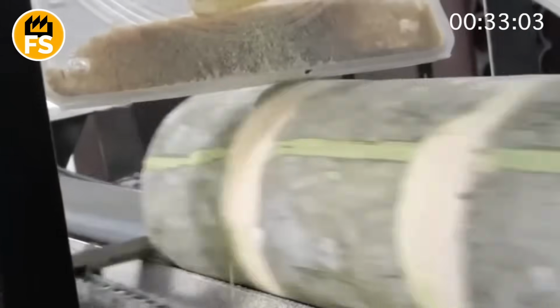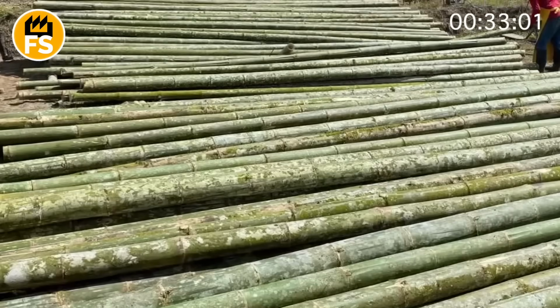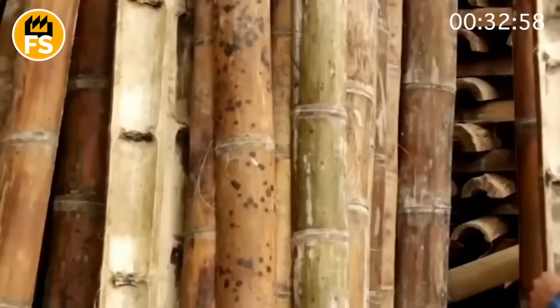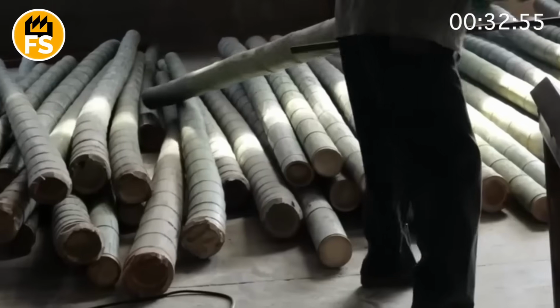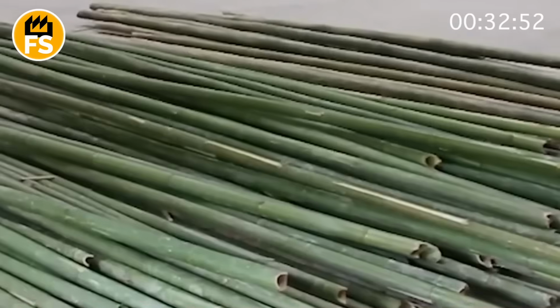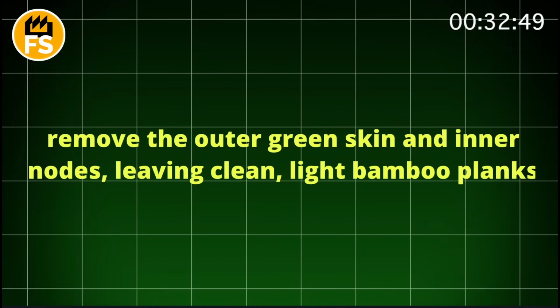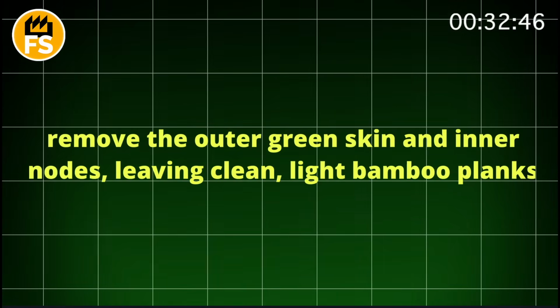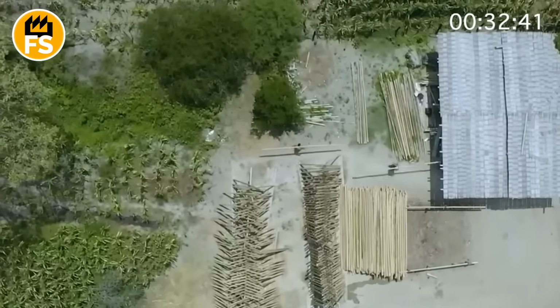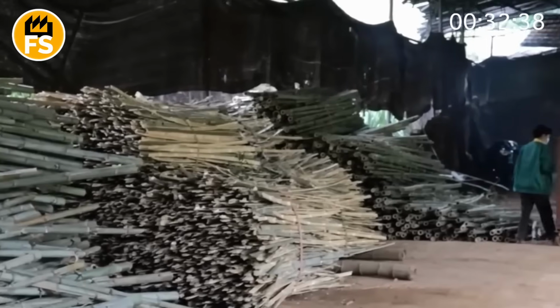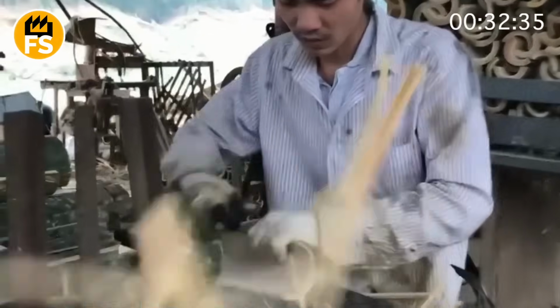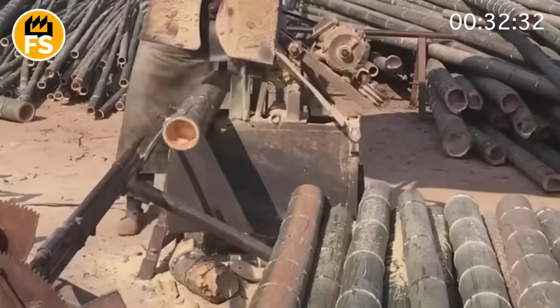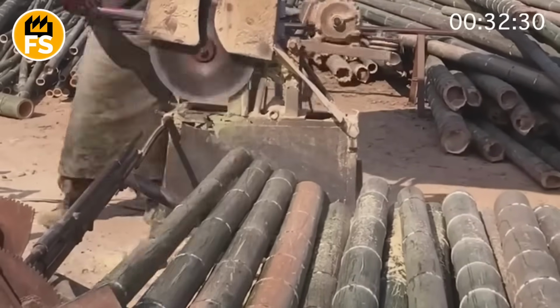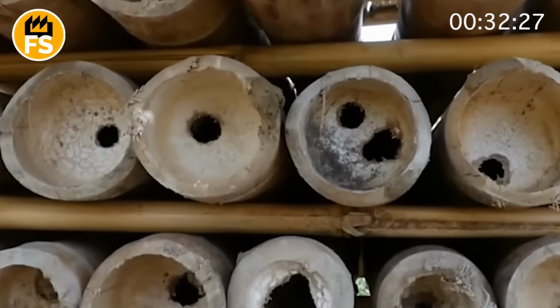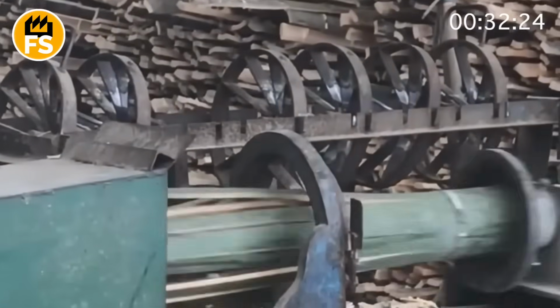First, the long stalks are cut into manageable sections. Then, they are fed into a special machine that, with a deafening crack, splits the round sections into long strips. The next step is to remove the outer green skin and inner nodes, leaving clean, light bamboo planks. But inside these planks still lurks an enemy of durability: starch and sugar, which are a favorite food for insects and mold. To get rid of them, the planks are submerged in huge vats of boiling water or a hydrogen peroxide solution for several hours. This hot bath not only sterilizes the bamboo, but also washes out all the nutrients.